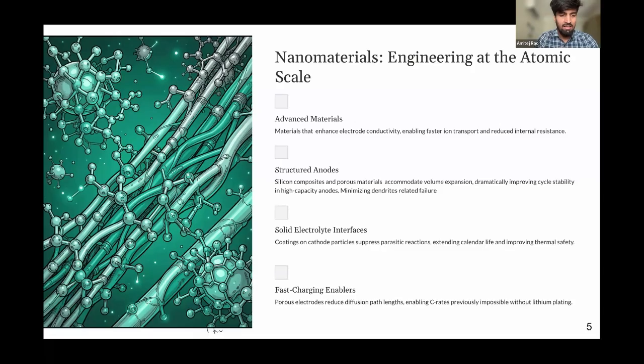In general, the lithium reacting with the solvent is an unwanted reaction, and that is what happens when the SEI layer is formed. It's an unwanted reaction, but it still is a protective layer. But excessive SEI interface formation would lead to capacity losses. So it has to be an optimized balance between the thickness of the SEI layer and preventing degradation more and more.